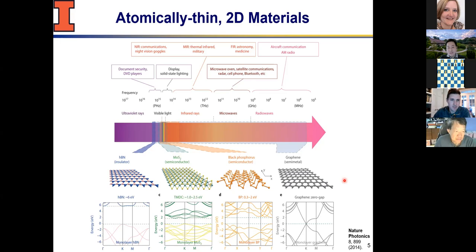But of course, there are lots of other materials that became very interesting once you know how to either make one layer of material by chemical vapor deposition process, or when you're able to use brute force, or mechanical exfoliation, using scotch tape to tape it off from the bulk crystal. That takes a lot of skill, but it's possible, and you can start to look into things that are semiconducting to insulating.